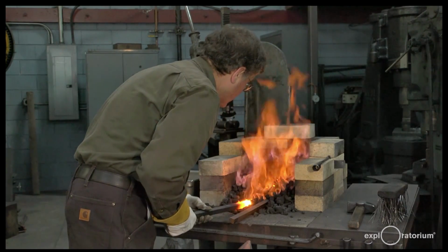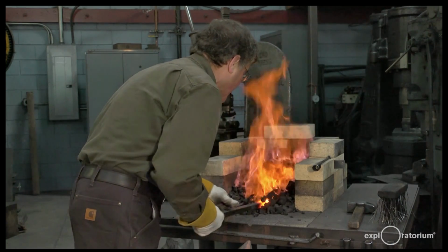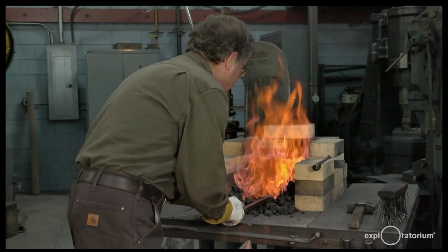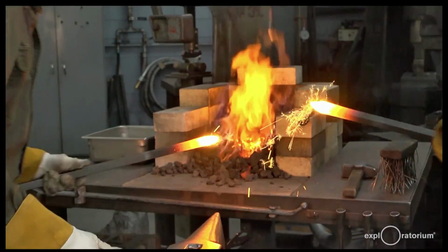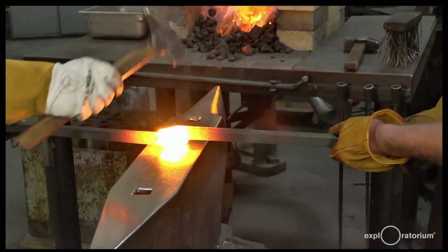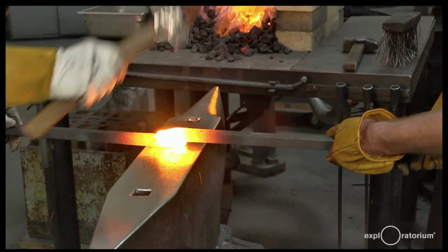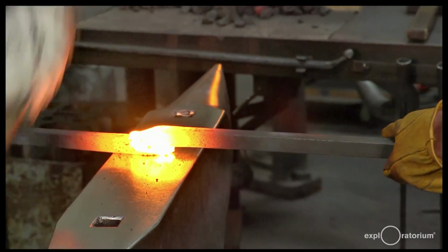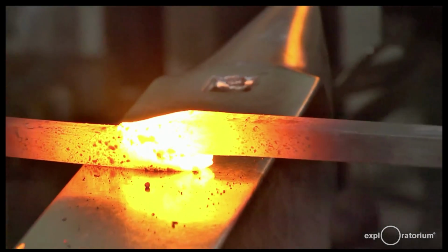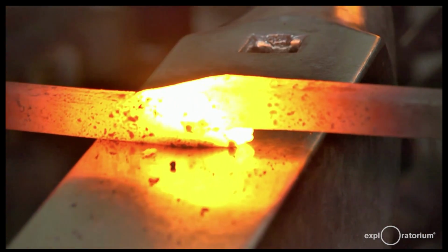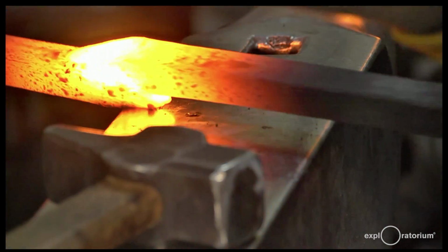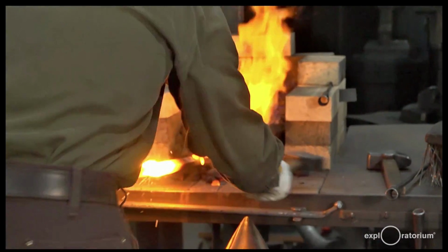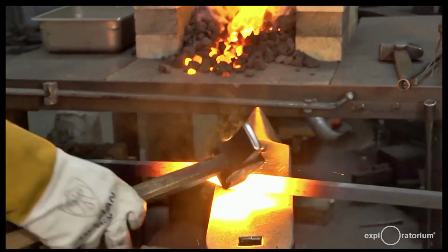So now they're going up to 2400 degrees or so. And then there's sort of a choreography of getting the weld together. There's a certain sound that tells me that these pieces are welding right now. But I can't finish the weld in one heat. It has to go back in probably 4 or 5 times to get everything finished.